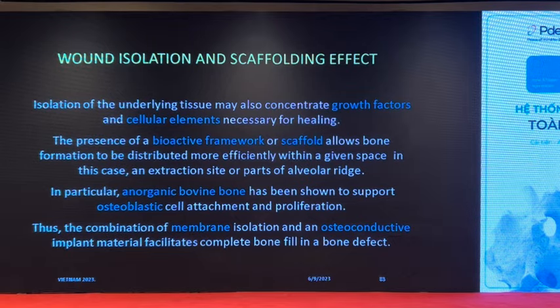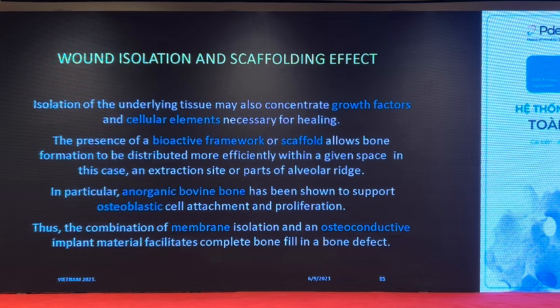Isolation of the underlying tissue may also concentrate growth factors and cellular elements necessary for healing. The presence of a bioactive framework or scaffold allows bone formation to be distributed more efficiently within the given space, in the extraction site of the alveolar region. In particular, anorganic bovine bone has been shown to support osteoblastic cell attachment and proliferation. Thus, the combination of membrane isolation with an osteoconductive implant material facilitates complete bone fill in a bone defect.